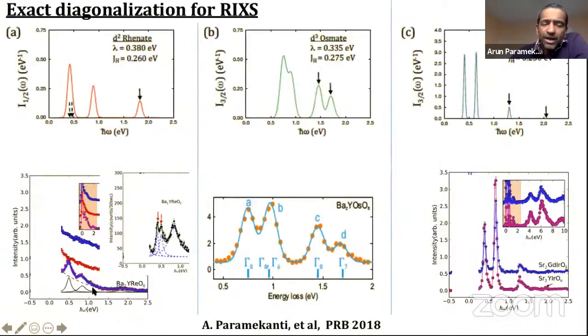And in fact, it leads to a structure of an excitation spectrum, much like for electrons in an atom, right? One can do a very simple toy model where you just take this spin and orbital angular momentum and add interactions, and you can very easily reproduce the kind of spectra for these resonant inelastic X-ray scattering experiments, where I've compared calculations that I've done with these RIXS experiments, and one can reproduce these structures reasonably well.